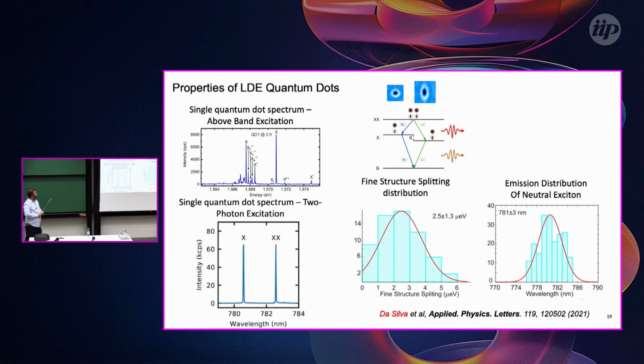Okay, this is the spectrum of isolated gallium arsenide quantum dots under above-band excitation. When you use above-band excitation, you can see a lot of charge carriers like the neutral exciton, the biexciton, and trions. You see a lot in the spectrum. But if you use two-photon excitation, you can make the spectrum cleaner, and you can just see the neutral exciton and the biexciton state.